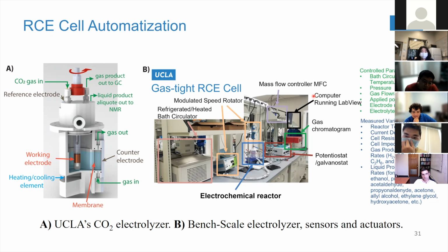Yes. Okay, cool. Another follow-up question would be, have you thought about using that degradation data to potentially model the overall catalyst degradation, if that's possible? Yes, what we identified right now, the model that we have, is that degradation is a function of the integral of the current. So the higher the current that you have, the faster your catalyst will degrade. If you go to more negative potentials, probably the faster you make that carbon intermediate at the surface. We believe that the activation mechanism is probably through the creation of some graphitic carbon species at the surface of the electrode, which is accelerated as you run the system longer and as you pass more electrons. Yeah, cool, thank you.